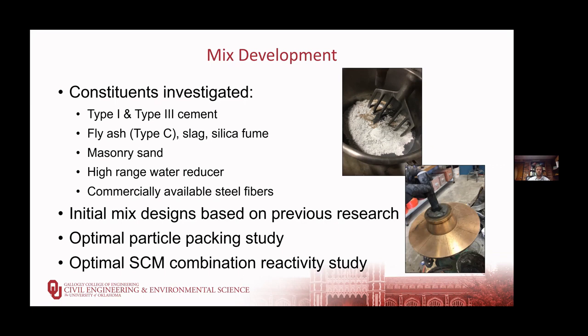And we took all of our materials, applied them to those mix designs, evaluated the performance, and then looked specifically at what we had to work with, our different possible constituents, and looked at optimizing the particle packing of the different gradations of those materials. We looked at about 3,400 different possibilities virtually to find the best particle packing for our materials. And then we also looked at the reactivity of our different cementitious materials to determine what would help us get the highest compressive strength.